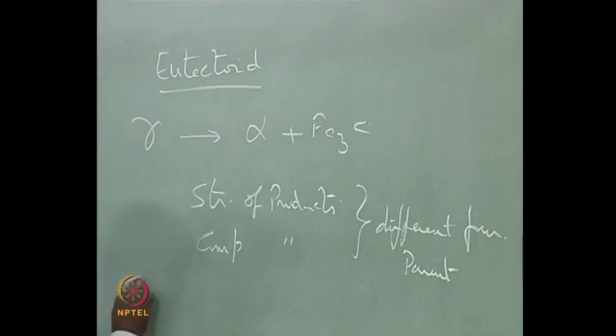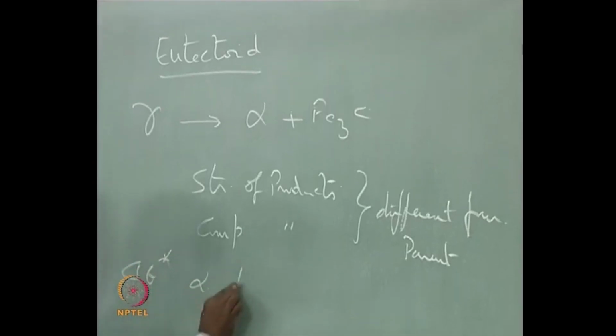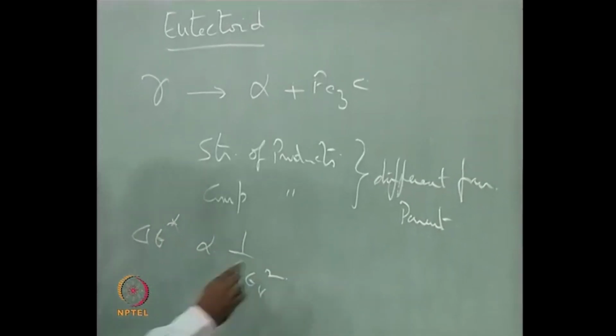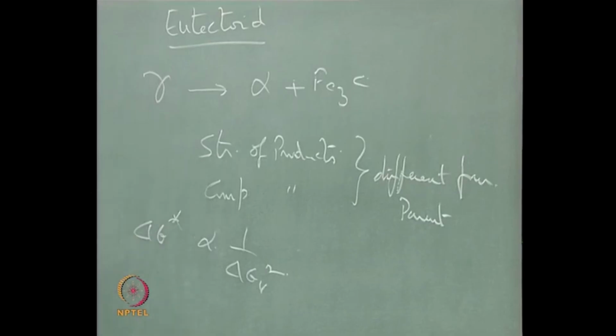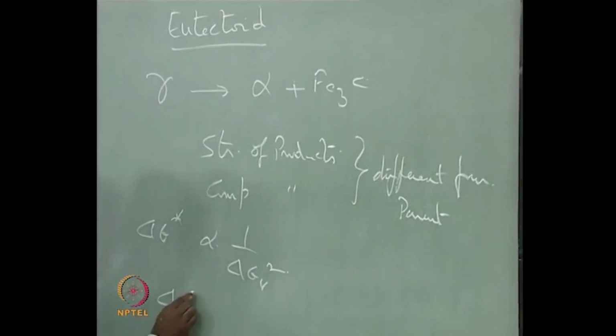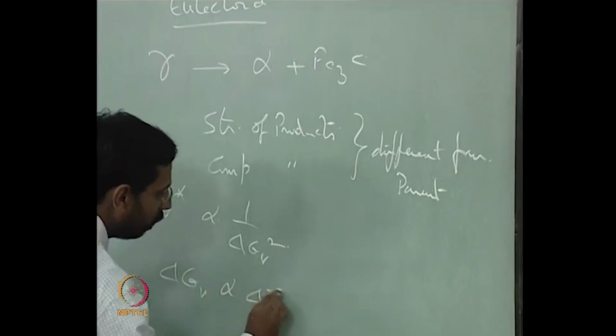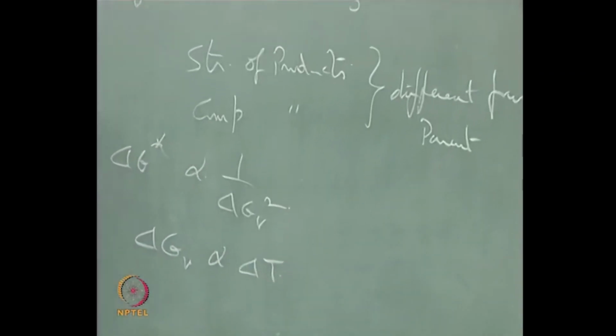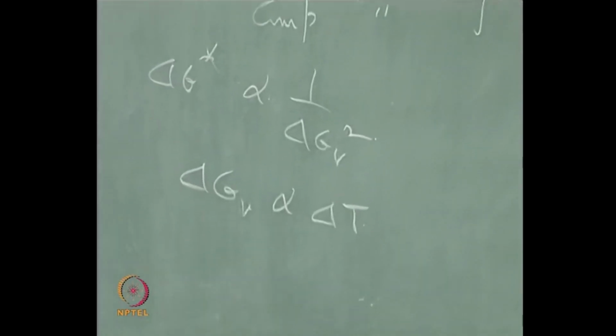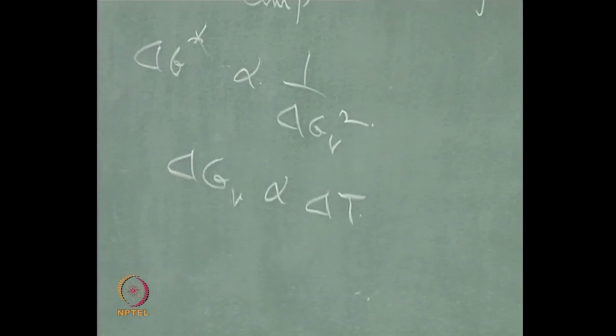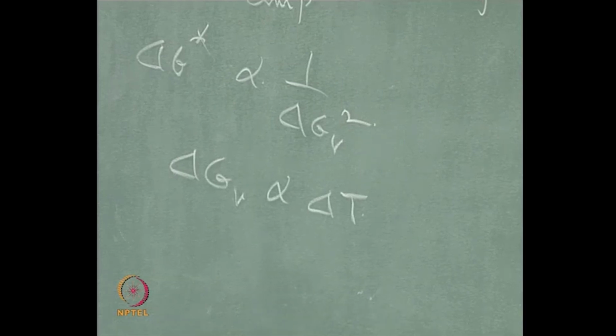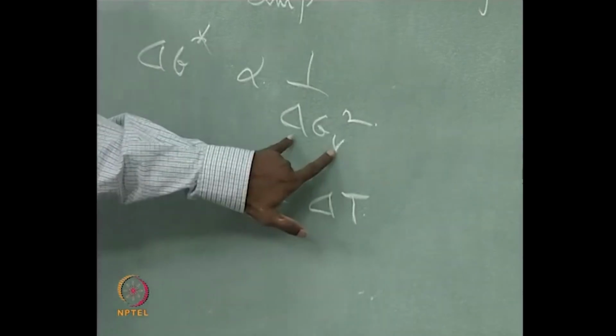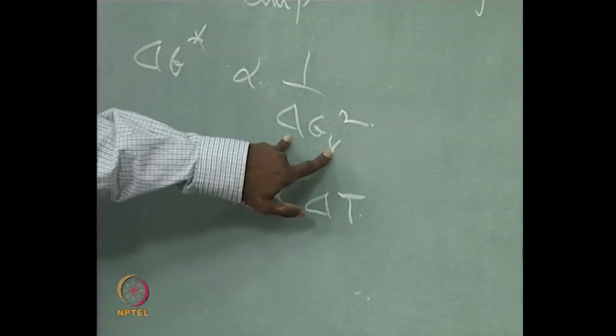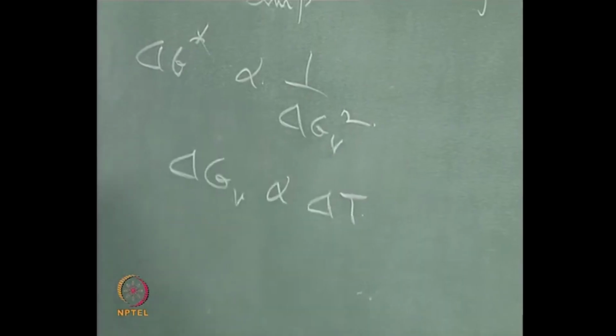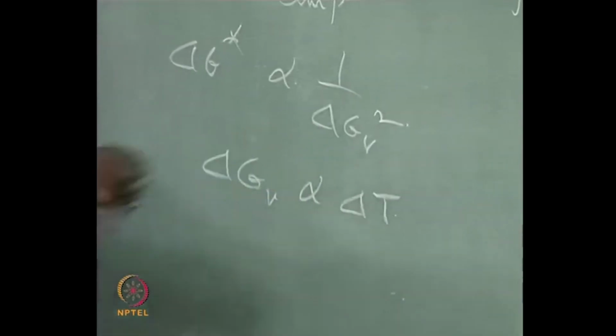We know that the activation energy for nucleation is inversely proportional to delta GV squared, and we also know that delta GV is proportional to delta T. Am I right? All this we have done, and the principles remain the same whether it is liquid to solid or solid to solid, excepting that in a solid to solid transformation we need to replace this part with something else. What is that? A combination of volume free energy and strain energy.